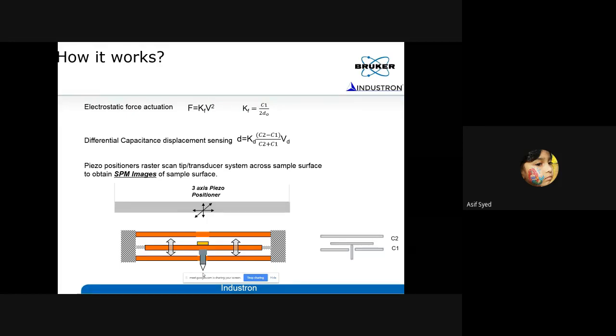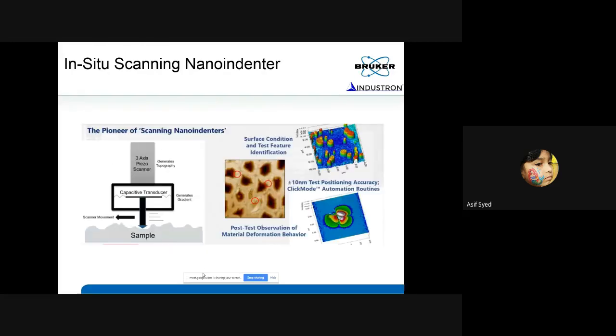Now, you can do this kind of topography down to like few nanometers. And so you have a nanometer resolution, high resolution scanning probe microscope built into a Nanoindenter system. So we call it scanning Nanoindenter. So not only can you use it to apply force and measure displacement like doing indentation, you can also use it to scan on a surface and get an image of the surface.